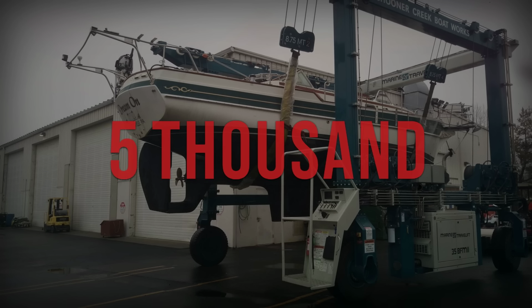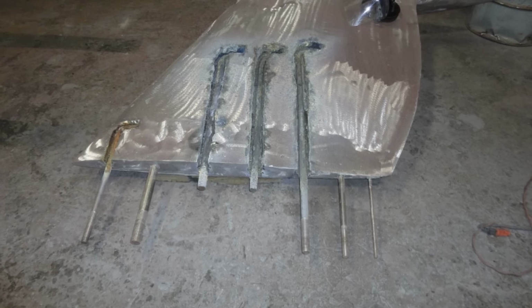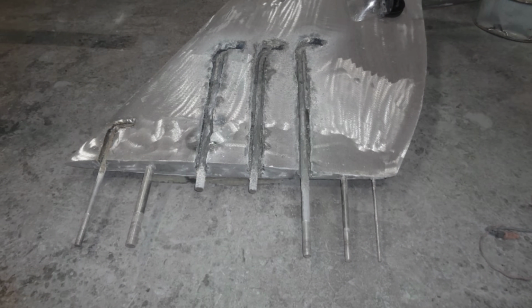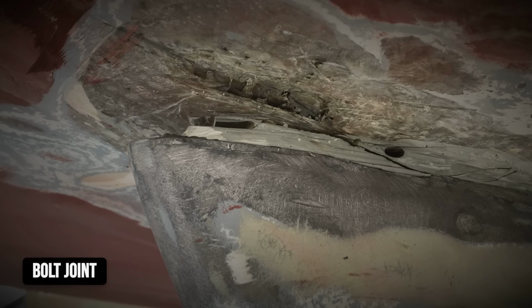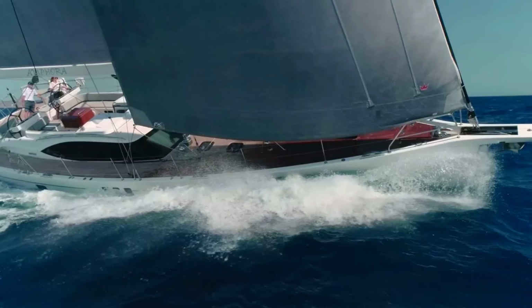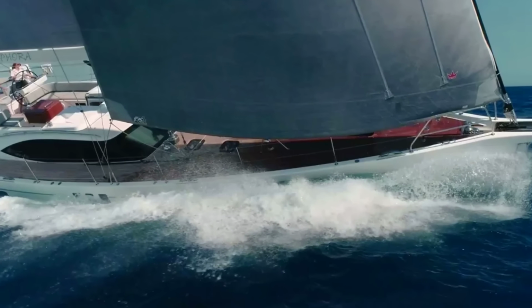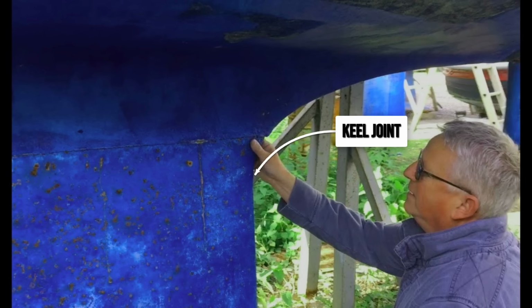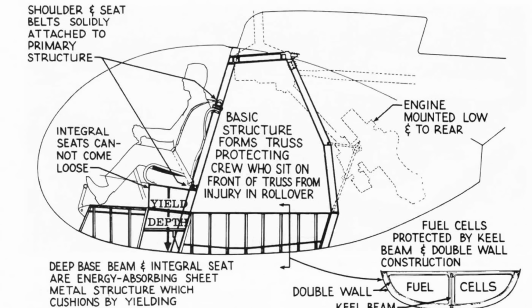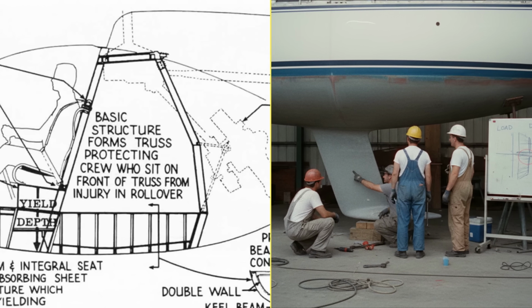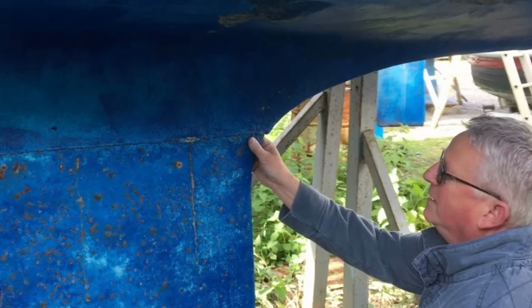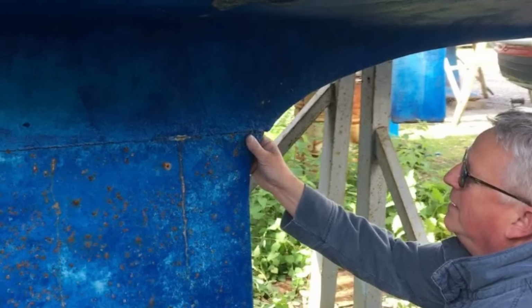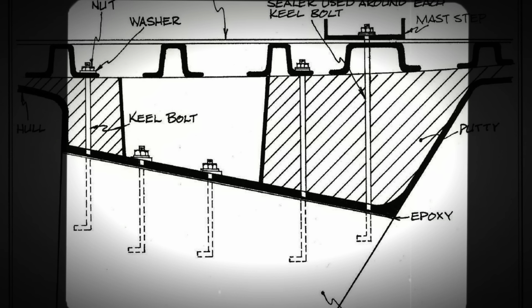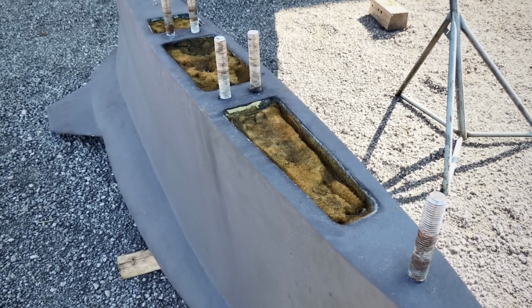The entire weight of the keel, sometimes upwards of 5,000 pounds, hangs from this small footprint, supported by a handful of bolts and the laminate around them. That weight is carried by a very small area. Every bit of righting force, every grounding shock, every load from the sea is funneled straight into that joint. Instead of being spread through a thick, continuous laminate, the stress is focused on a narrow band, just a few feet long and maybe a foot wide. Stress concentrates.